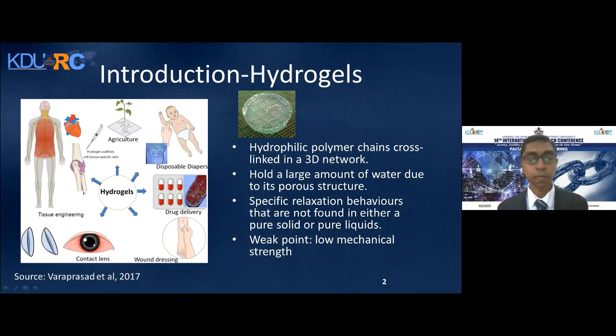So we investigated its ability to be used as a material for insoles due to specific behaviors such as relaxation behavior, cooling effect, high thermal capacity, and better shear properties. But the main weakness of this material is low mechanical strength. This has to be overcome and tested if we use hydrogel for load-bearing applications. So let's see what the maximum stresses acting on the material are if we use it under the foot.